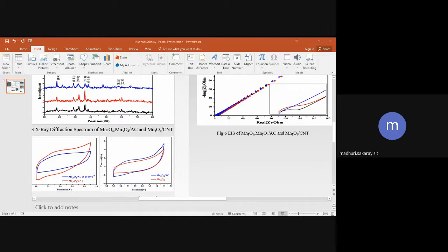Coming to the characterization techniques, the first one is Fourier transform infrared spectroscopy, and these were confirmed with the bands in the literature. The bending at 650 is attributed to Mn-O and 1384 to the OH group, and 1631 and 3453 to OH, and the C-C stretching, attributed to the CNTs and activated carbon, is at 2920. The XRD analysis was confirmed with the JCPDS card numbers, and the size for the 1 to 2 ratio of manganese acetate and citric acid is 20.81 nanometers, and for the ratio of 1 to 4 it was 18.9.